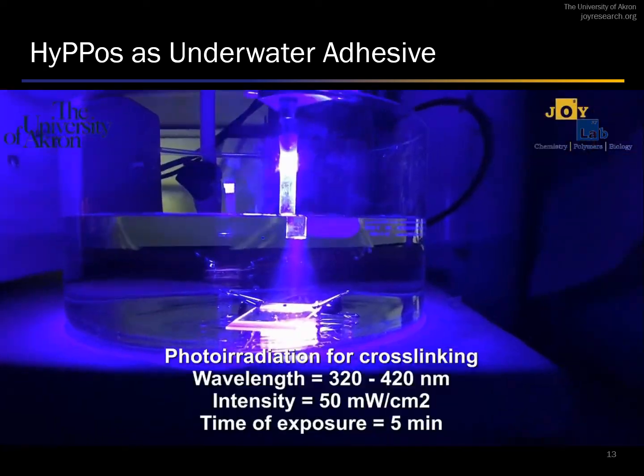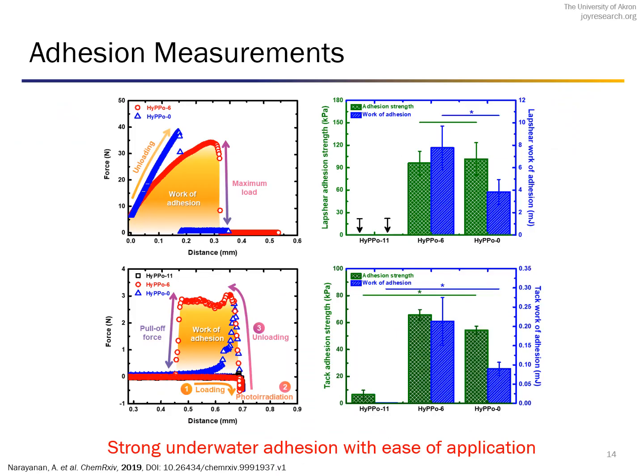And you can later cure this material using UV light, and it acts as a strong underwater adhesive, as you can see from the adhesion measurements here. Two methods of adhesion measurements were used. One, the lap shear on the top, and the second one is the tack adhesion measurement. This was completely done, spread, cured, and sheared in underwater conditions. And it shows one of the strongest coacervate-based adhesives reported in the literature with such rapid curing.